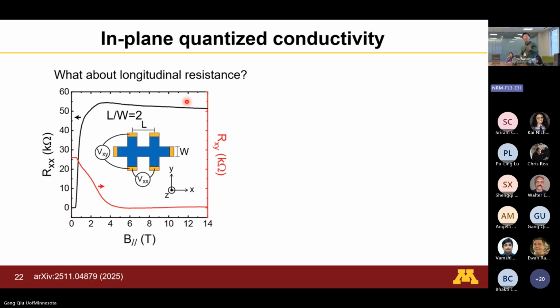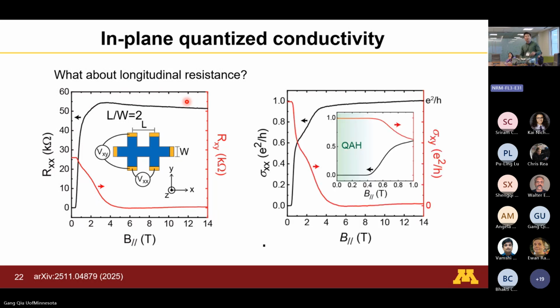If you look at the aspect ratio of the channel, it is 2. If you convert it into a conductivity or resistivity, this is not a random number. It's actually exactly e squared over h. So in this in-plane configuration, the longitudinal resistance actually is quantized.